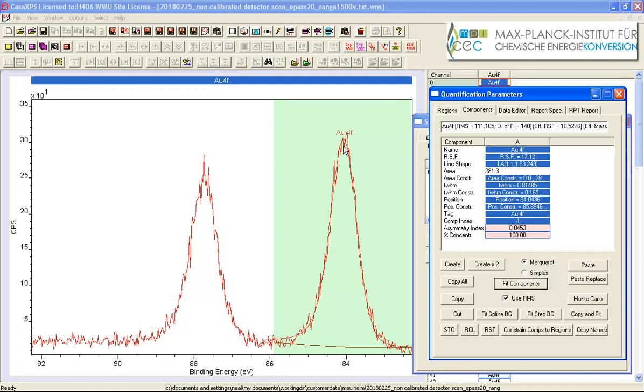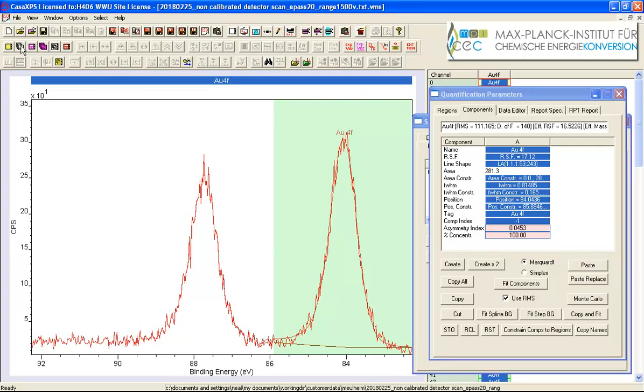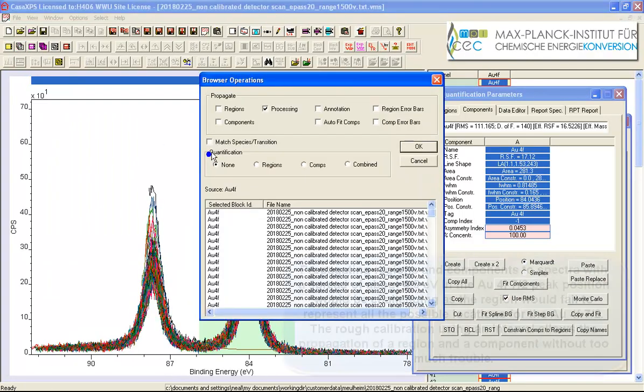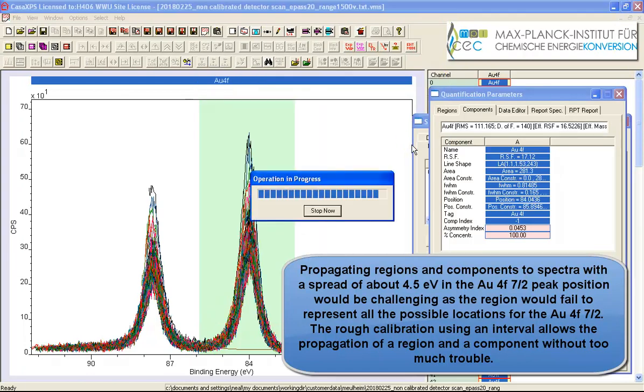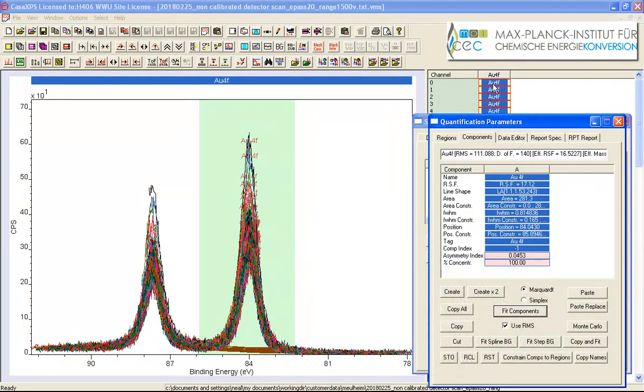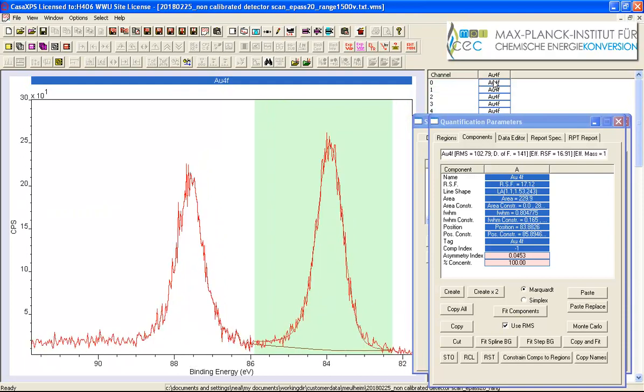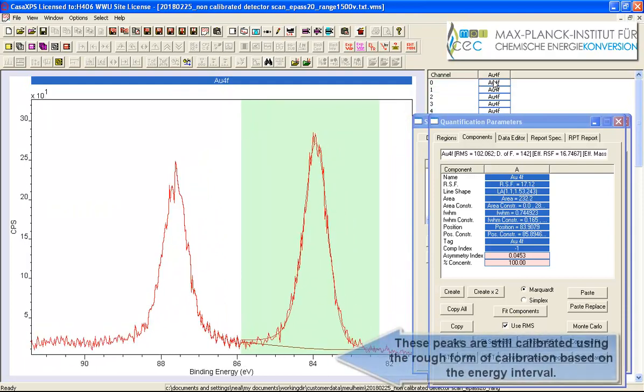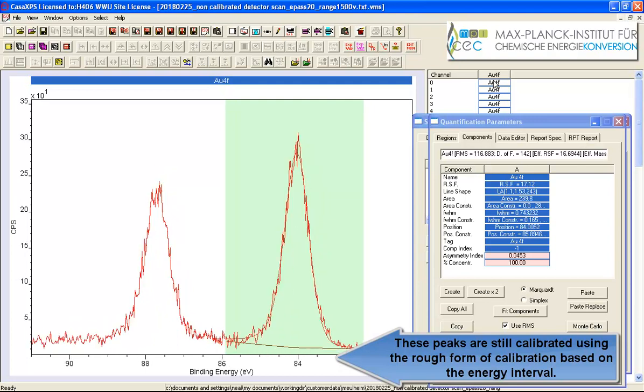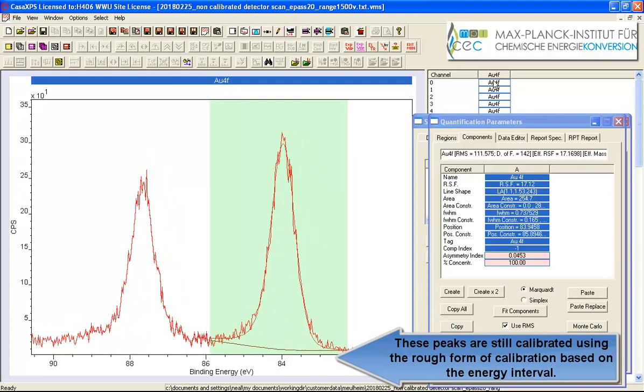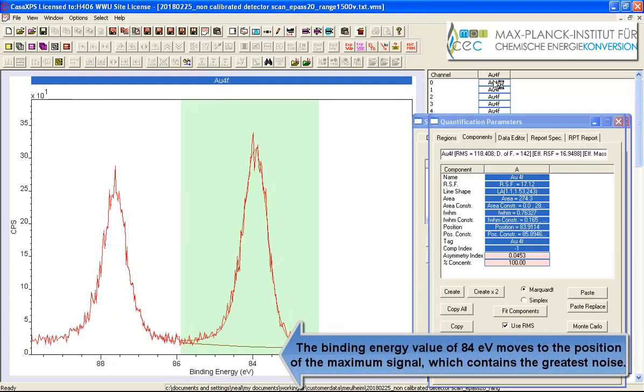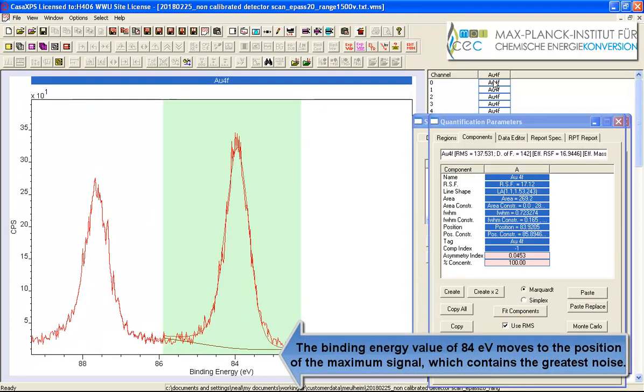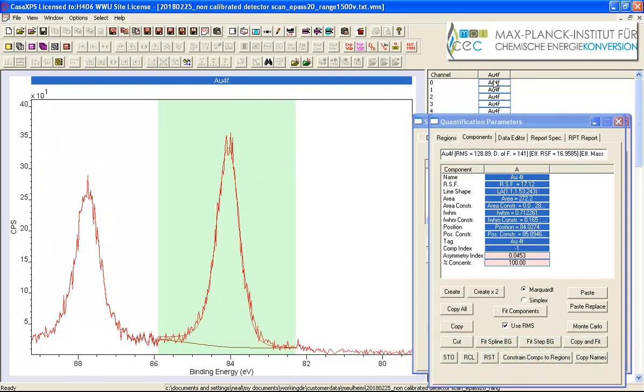And then what I can do because I've got these aligned I can simply propagate this in terms of region and the component and I'm going to auto fit so having auto fitted I now have a fit and if I step through you can see we've got a peak and you can see it's the binding energy scale that is moving as I step through these data. The peak is slightly jittery if you look at that. The binding energy scale you can see that it doesn't move smoothly and that's why I'm performing this second operation.